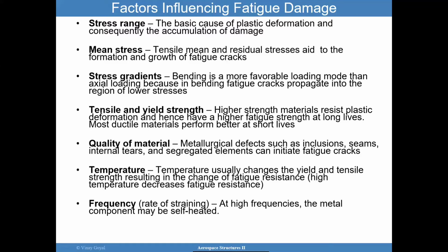Tensile and yield strength: higher strength materials will resist plastic deformation, especially if you have higher yield. So if you have a better yield performance, higher fatigue strength occurs, and so you have longer lives. Most ductile materials will perform better at shorter lives. The quality of the material is important. So if you have metallurgic defects such as inclusion seams, internal tears, those could be points of initiation for fatigue. Temperature usually also changes the yield strength, and as a consequence, it will impact the fatigue resistance. That's an important consideration in these applications.